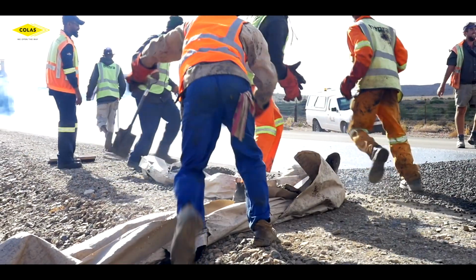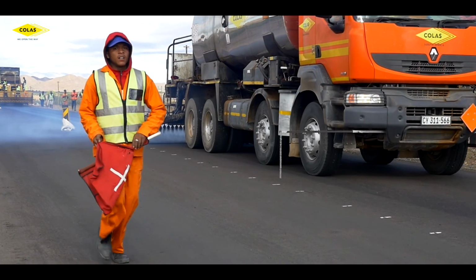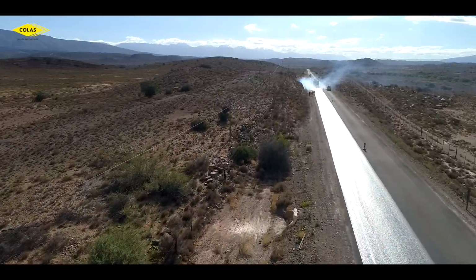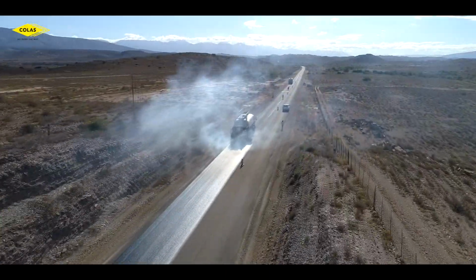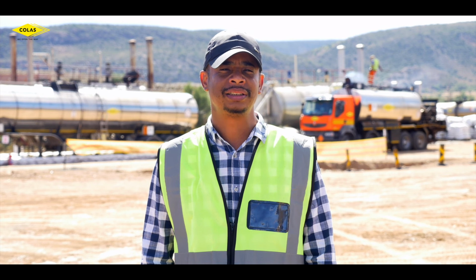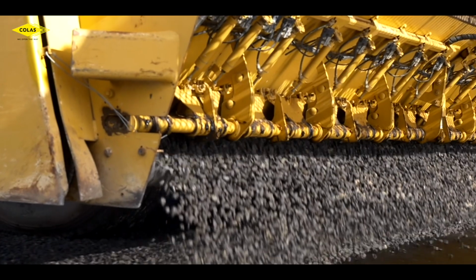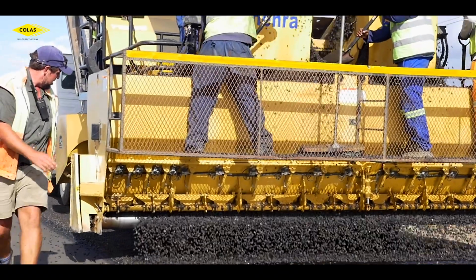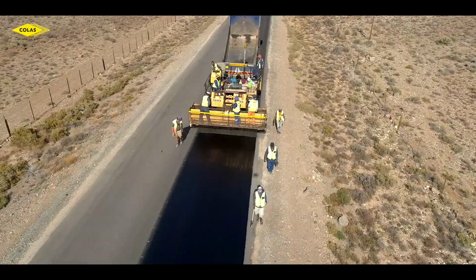Bitumen rubber is a non-homogeneous product that has a straight run 70/100, a fair amount of rubber crumbs, and a small amount of aromatic oils. Bitumen rubber can be sprayed on a road surface at temperatures anywhere between 185 and 200 degrees. It is very good, especially with surface cracks in excess of 5 millimeters. Also, you have minimal bleeding, whereas conventional bitumen products or polymer binders will bleed at the high temperatures that we spray at.